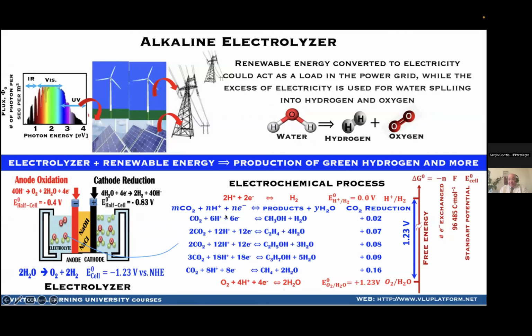And as you see here, between the production of hydrogen and the production of oxygen, you have thermodynamically 1.23 volt. And there are many reactions for the fixation of CO2 and fabrication of alcohol, ethanol, methanol, etc., and other compounds which can be used as fuel. But as you see here, between the oxidation of water and the reduction, these two reactions here in red, you have a very critical potential in order to get one reaction here. So the situation and the challenge are very big. I'm talking about electrochemistry, of course.